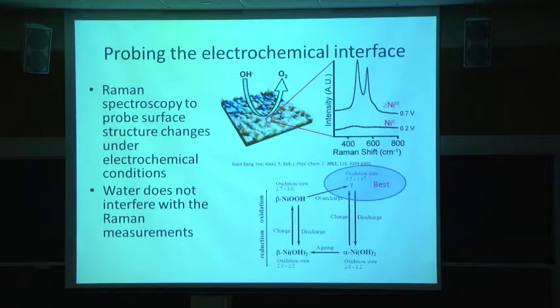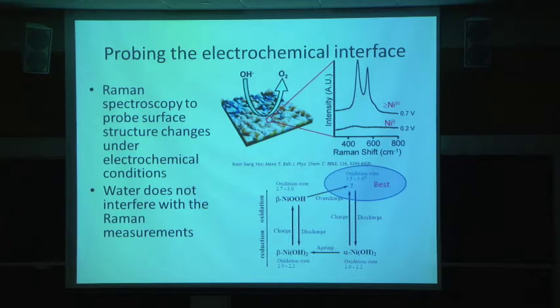So people have studied nickel oxide for a long time for battery applications. These two phases down here are not conductive, so they're not seen very much in electrochemistry. But these form this nickel oxyhydroxide phase. There's a beta phase and there's a gamma phase. And the gamma phase is believed to be the best phase for oxygen evolution because you have the highest oxidation state of nickel in here. It's also a little bit more open. And so we were interested in wondering, could these electrolytes be affecting the speciation of the nickel oxide hydroxy phases that are forming in here?